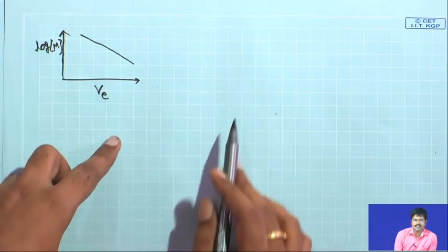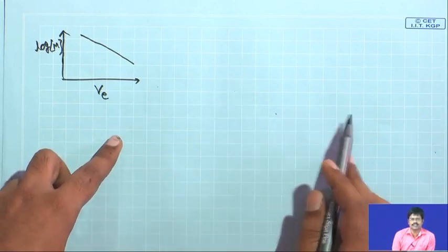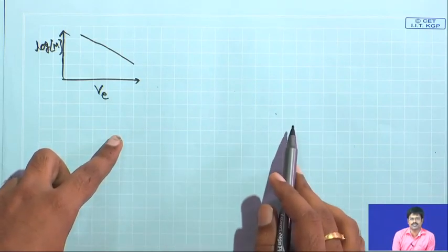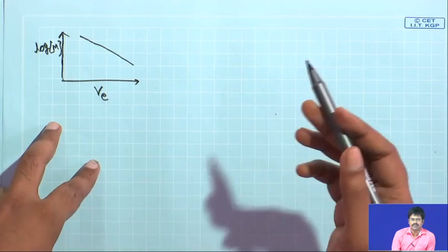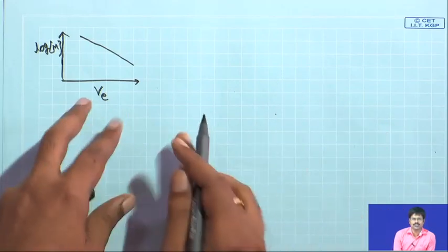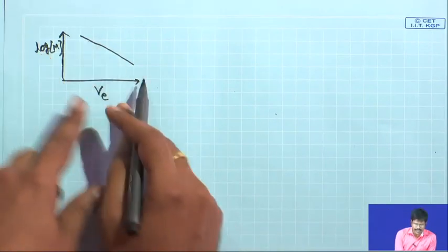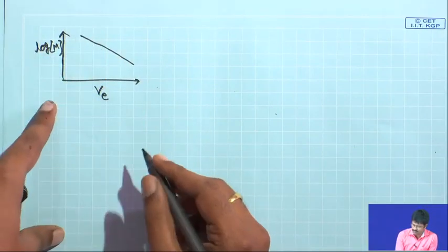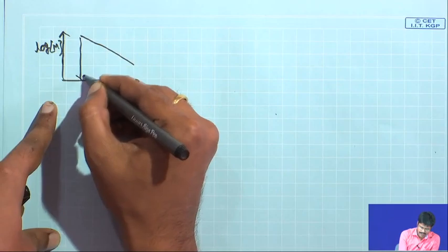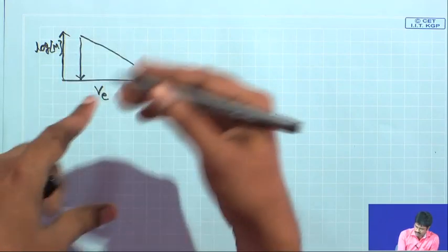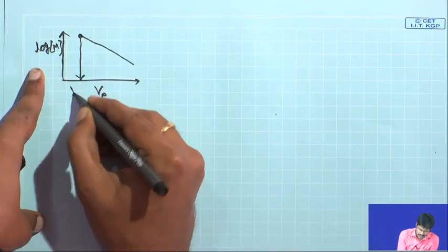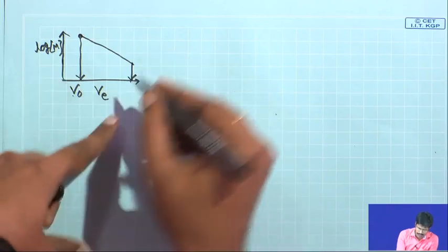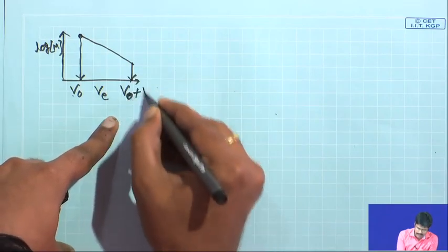If you see in the initial diagram, on the y axis we wanted to put weight fraction, on the x axis we wanted to put molecular weight. So, the elution volume has to be related to molecular weight, and with this relation you can directly relate elution volume with molecular weight. This is a point where you have total exclusion of the molecule, which is V_0, and this is a point where you have total permeation of the molecule, which is V_0 plus V_i.